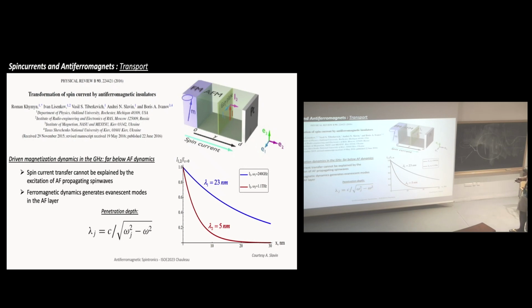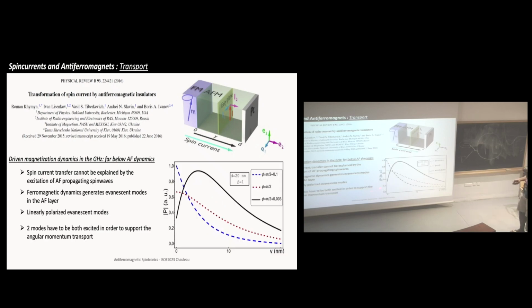But what I want to remind you is that those two modes are linearly polarized, and linearly polarized waves cannot carry a spin current easily because there is no ħ. So if you want them to carry things, you need to combine them, because by combining two linearly polarized modes, you can have a circularly polarized mode. They made this little model, with some decoherence, and the nice thing is that they managed to reproduce the fact that they saw a maximum of transmission at some thickness. If we consider those two first papers and this one, that was really what triggered the field of oxide antiferromagnetic spintronics.